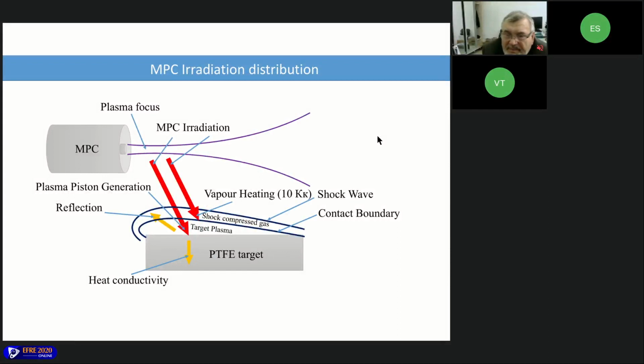From the interferograms, we see the energy distribution on the target. The falling radiation goes to heat conductivity, reflection, shock, compressed gas generation, and absorption in the target plasma for heating and further transmitting.